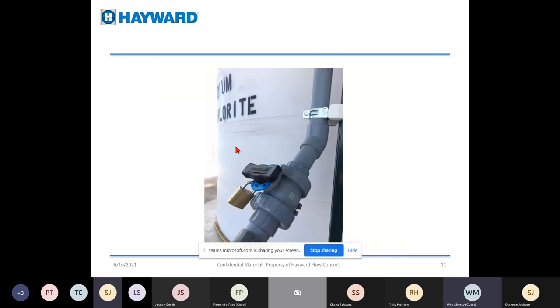Sodium hypochlorite, again, is a very aggressive chemical. PVC and CPVC both withstand sodium hypochlorite just fine. One of the things we did mention earlier is that you also have to factor in the elastomer or O-ring material that's used in these valves. So when chemicals are being used in a process, consulting a chemical compatibility chart to verify compatibility with the valve and pipe body material and also the O-ring material is very, very key.